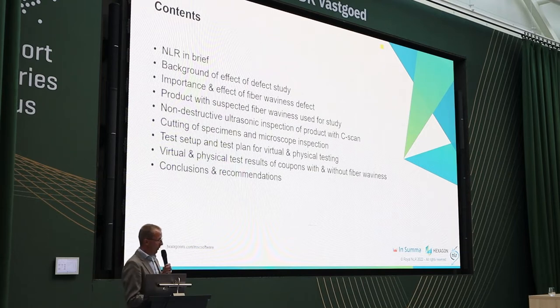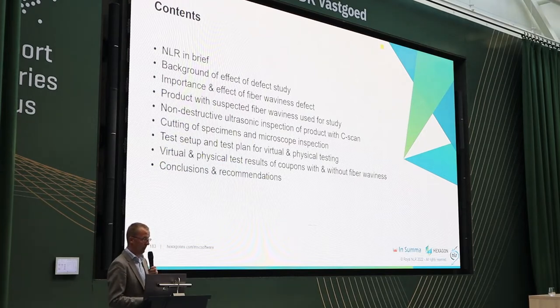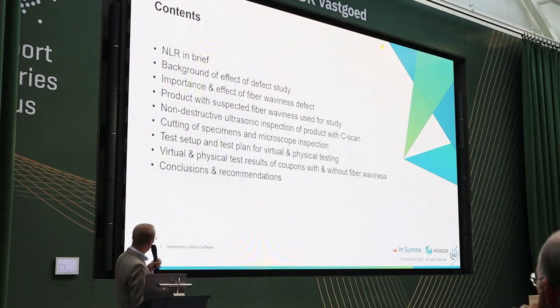I was looking for a sample to test, to cut some coupons from, and do some physical testing compared with virtual testing. So I found within NLR some product that might have fiber waviness. To prove that it has indeed fiber waviness, I made a C-scan, and we'll talk about that. And for the simulations, I also need certain parameters for waviness, like wavelength and amplitude. So I based it on microscope inspection. I'll show you later. Then I'll talk about the test setup and the test plan that I had for the virtual and physical testing, and I will show you